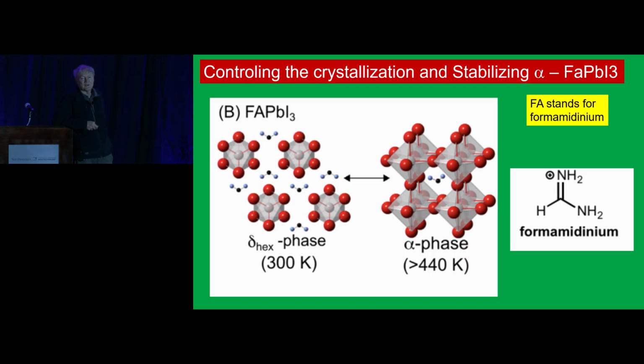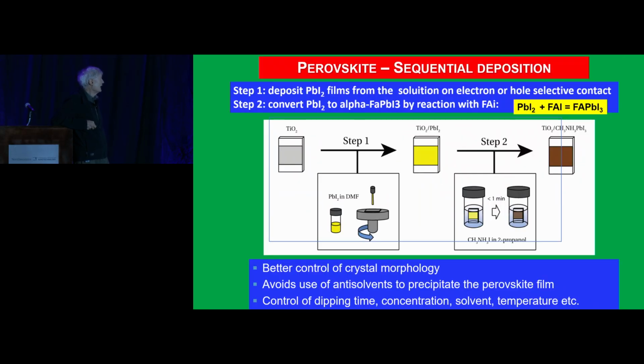You can do this in different ways. You can add foreign ions like cesium or other cations. But of course, the nicest thing would be if you could just use pure material and still keep it alive at room temperature. And so this is possible in different ways. I'm now using the sequential deposition.